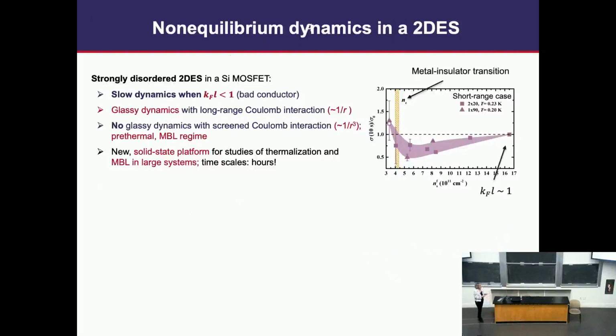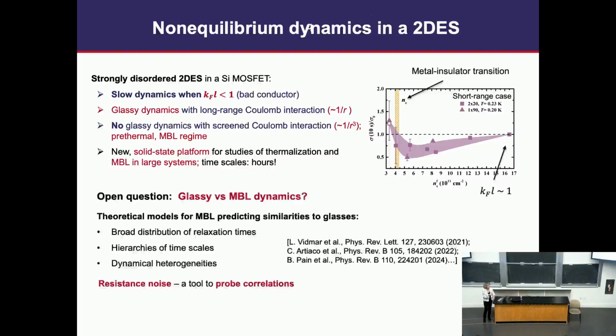So basically, what I showed you is that this is a wonderful system in the regime at low densities where disorder dominates. The dynamics is always slow. In the case of a long-range Coulomb interaction, it is glassy, but glassiness does not survive if you reduce the range of the interaction - instead we see this pre-thermal or MBL regime. So basically this establishes this system as a new solid-state platform for studies of thermalization in large systems, which is what was needed.